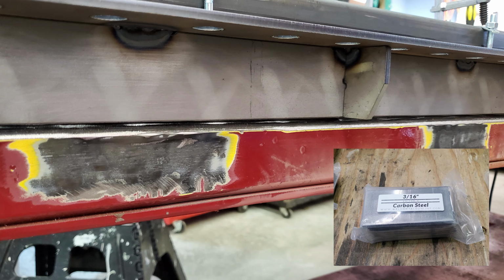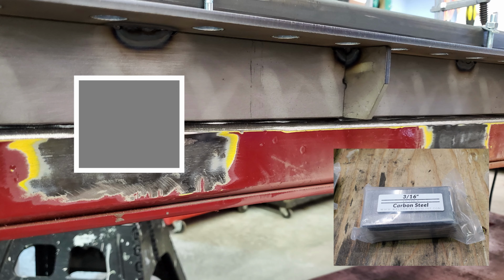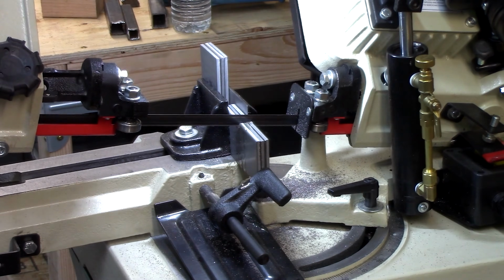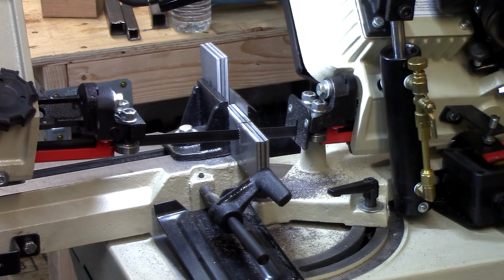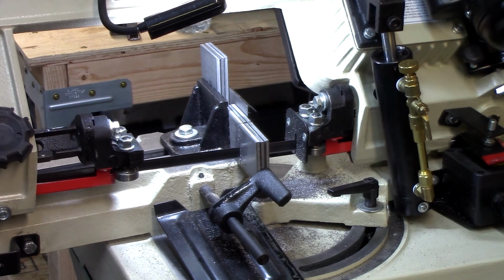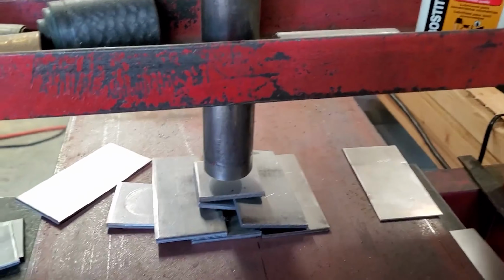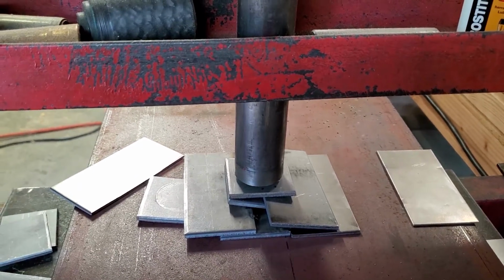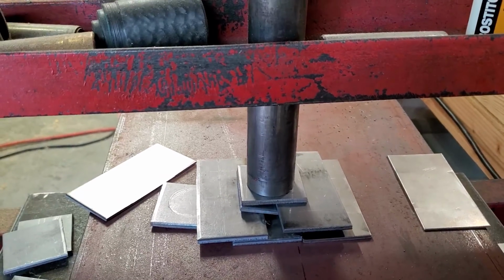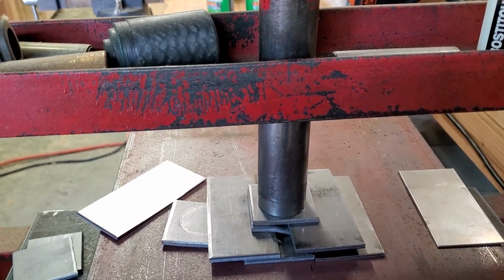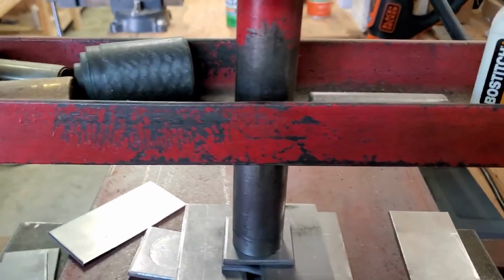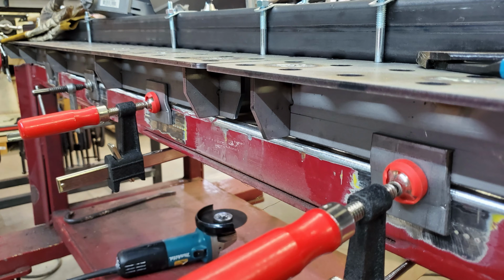I decided to use welding coupons that would overlap the bottom of the ribs and the top of the red frame base and weld along the vertical sides of the coupons, thinking this would limit the warping applied to the tabletops. I cut my 2" by 4" welding coupons in half to make 2" by 2" squares. A problem though was that the tabletop's ribs were just slightly wider than the red frame's base. Using my pneumatic press, I gave each of the coupon squares a slight S-bend. The coupons fit and looked pretty good, so I went ahead and welded them all on.